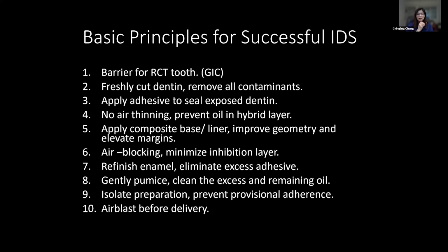Second of all, we have to prepare the dentin freshly and remove all the contamination material to create a fresh, clean surface before we do the immediate dentin sealing. And then we apply the adhesive to seal the exposed dentin. So basically, this procedure is for dentin. We don't need to apply it all over the tooth, just to the dentin. And after we apply the bonding agent, we don't do air thinning because we don't want any oil or any contaminants from the air spray.